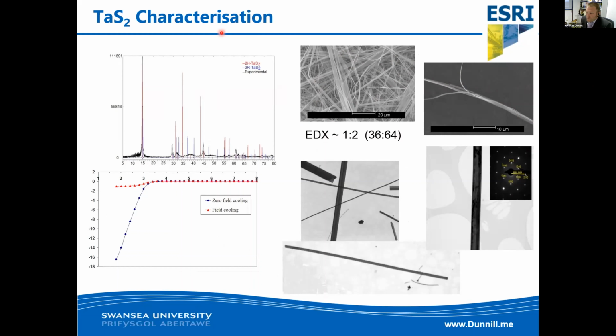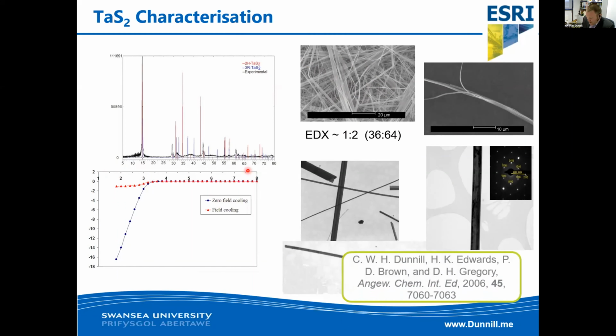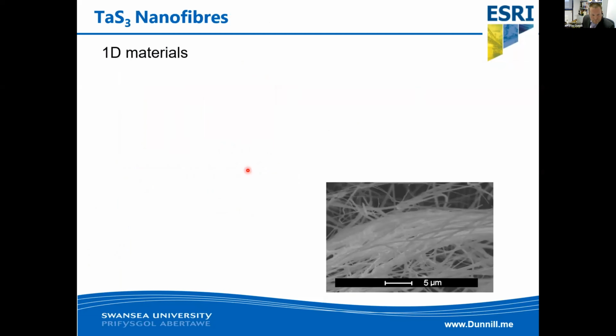disulfide. So the difference between the different polytype structures is due to both the coordination of the tantalum atoms with respect to the sulfur atoms within the tri-layer sandwiches, and indeed the alignment of the sandwiches themselves. We can use specific heating regimes to isolate any of these three structures, and the 1T actually shows superconductivity down at very low temperatures. And again, that gave us a few interesting publications, one of which was an Angewandte paper showing the syntheses.